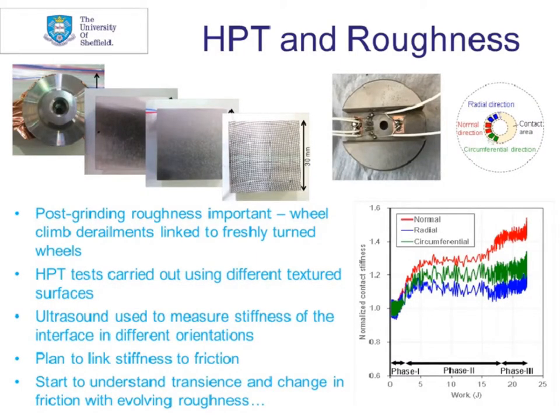Obviously, putting roughness onto the rail changes the contact conditions quite considerably. You know, in terms of grinding, we're going up to roughnesses of maybe 10 microns, which tribologically is very, very rough. So we need to look at how the contact may evolve post-grinding. It's been noted in the past that wheel climb derailments can occur shortly after wheels have been turned or rails have been ground. So it's obviously potentially creating a very high friction contact conditions under some circumstances